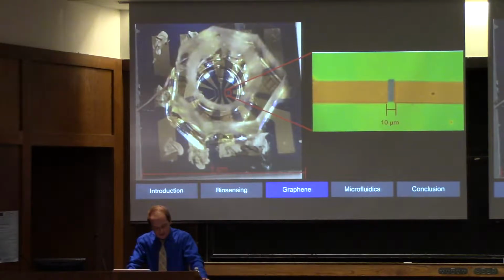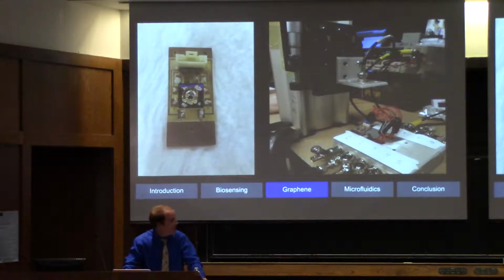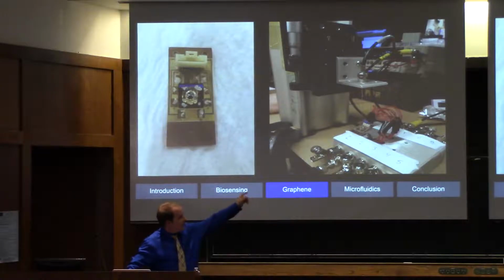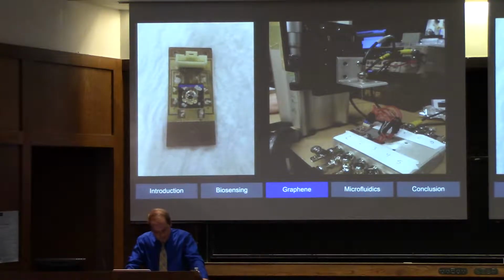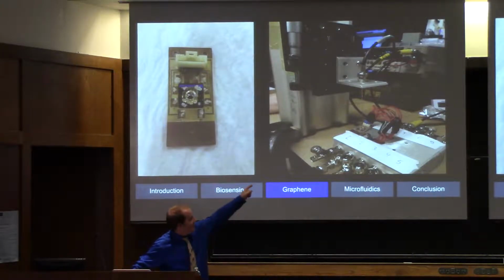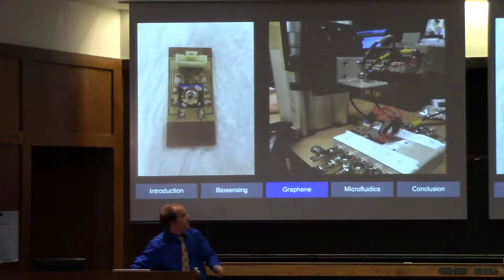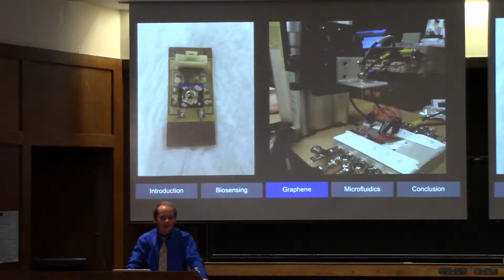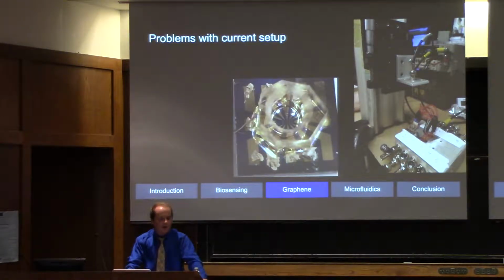We then put these chips onto a PCB, which attaches to this breakout box, which is this silver box you see here with the red wire sticking out of it. The breakout box basically just connects to a multimeter and allows us to run our resistance measurements. The gate voltage is applied via this electrode. You can barely see it there. It's the thing hanging from that silver piece. It actually goes into the liquid and serves as the gate for our gate voltage measurements, with the liquid serving as a dielectric.